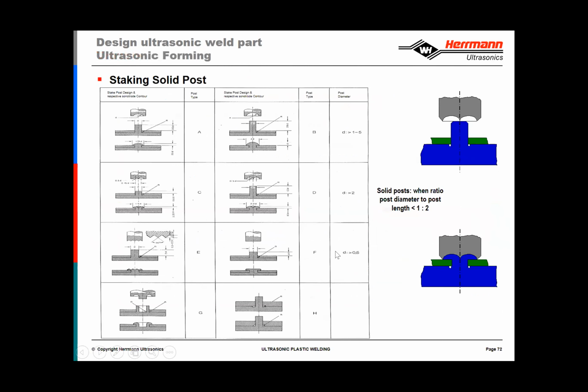Staking of solid posts, we have a little bit more flexibility here, and you can see the different designs that we can use, anything from a low-profile dome to a knurl or just a flat. So again, the detail is in the sonotrode. There's no joint design, there's no energy director here. The point of the sonotrode acts to initiate the melt, and again, melt volume encapsulation is quite critical.